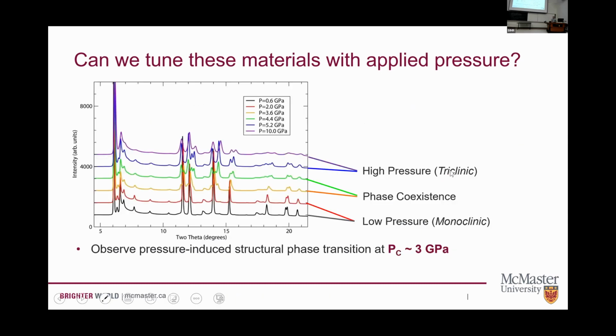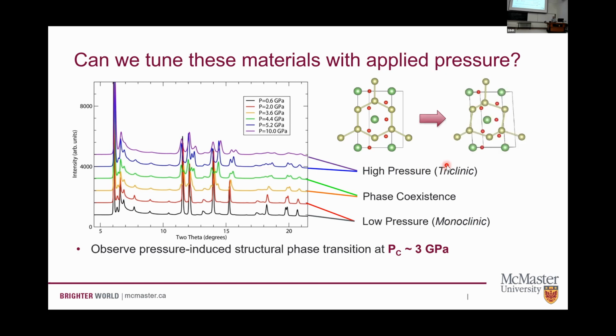You can do synchrotron diffraction, so not resonant, just looking at the crystal structure. And what you find is a pressure-induced structural transition at about 3 gigapascal, where we see a lot of those orbital changes happening. We go from a low-pressure monoclinic structure to a high-pressure triclinic structure. And if you refine these powder diffraction patterns, what looks like is happening is we're forming these little dimers. So the hexagon starts as regular, and then it forms these little iridium-iridium pairs once you go up to high pressures. Okay, so this data is interesting. Also not a quantum spin liquid, but one which we still have a lot of different experiments that we can do.